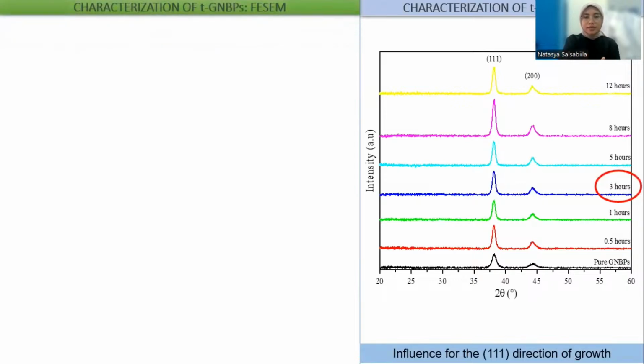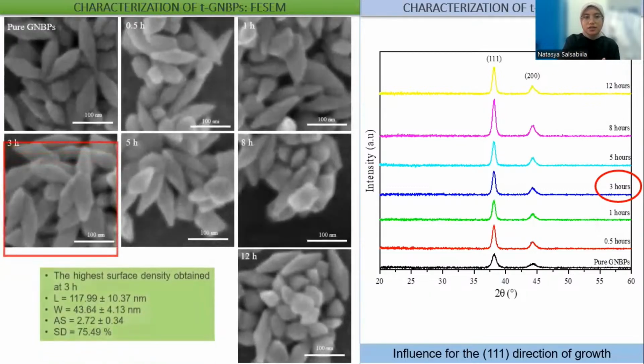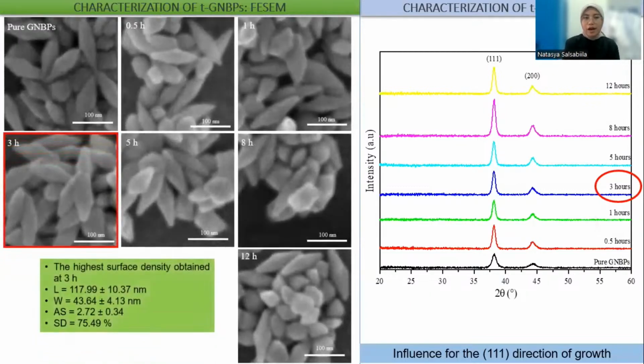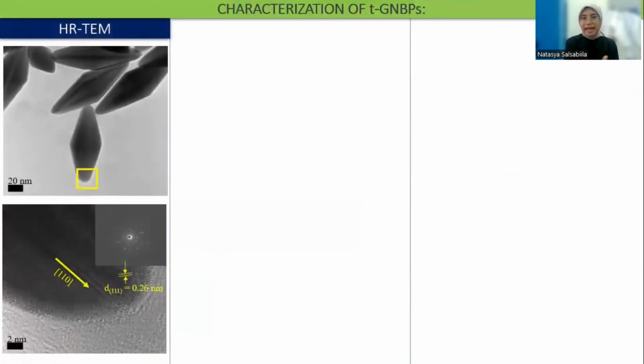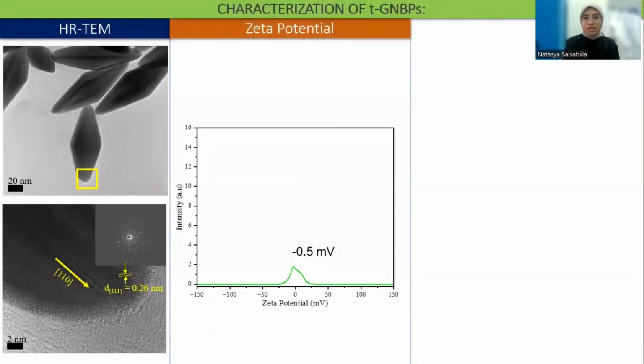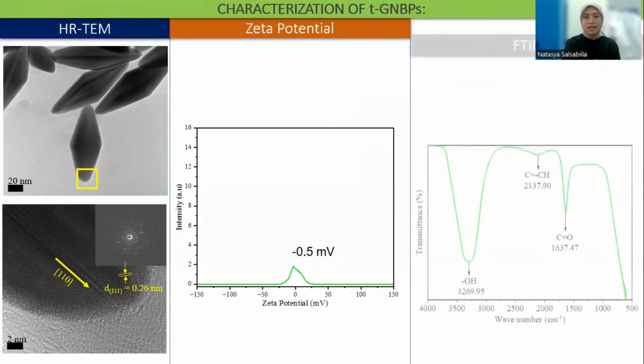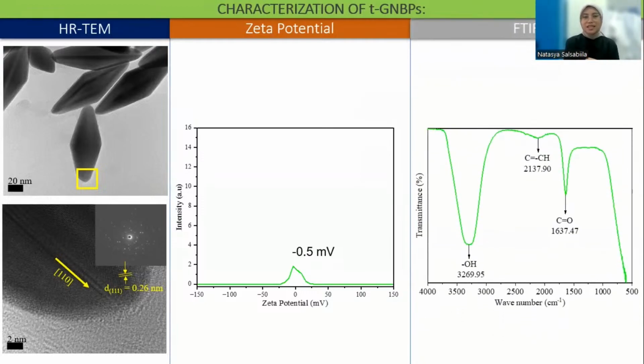but if we see here, the usage of thiol can influence the increase in 111 and 200 planes. Next, FESEM. So from FESEM, the highest surface density is obtained at 3 hours as well, with a value of over 75%. From TEM, we didn't see any morphological change as in AGNBPs before, with zeta potential value measured at minus 0.5 millivolts, which decreased from pure GNBPs. And the last one, from FTIR, we obtained that the usage of thiol groups to functionalize the surface of GNBPs can also affect the wave number shift.